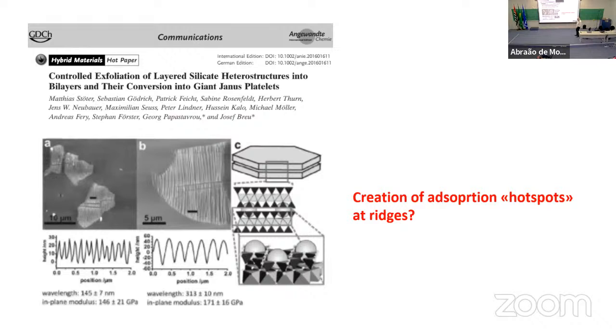Let's say that you have a ridge like this, then you expose the internal of the clay structure more than if you are in a valley of this wrinkling. So you will probably have some variations of electric field. You will have different electric fields on the ridges compared to the valleys. So this is something we are looking into with simulations together with Alessandro and Caetano. Then also when we have done that for a while, we will do experiments.